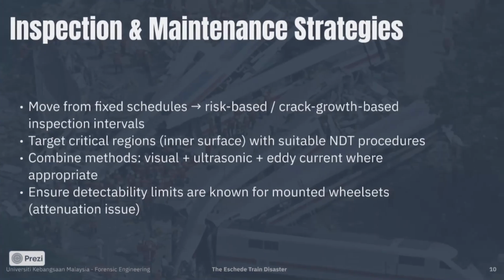Second, inspection and maintenance strategies must be adapted to fatigue crack growth. Fixed time-based routines alone are not sufficient. Inspection intervals should be linked to expected crack growth behavior, especially in high-risk regions where cracks initiate internally. In addition, NDT procedures must account for detectability limits. For mounted wheel sets, ultrasonic sensitivity can be reduced due to signal attenuation at the axle-wheel interface, so inspection procedures and thresholds must be validated for the actual assembly. The goal is to detect cracks well before they reach critical size.